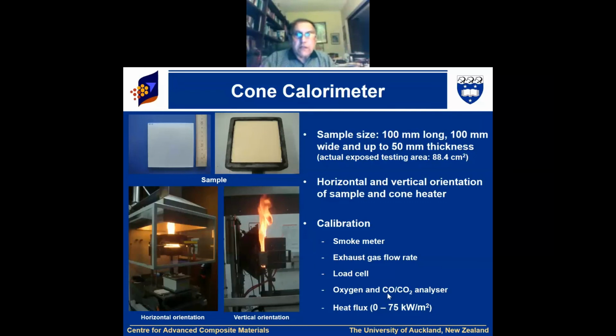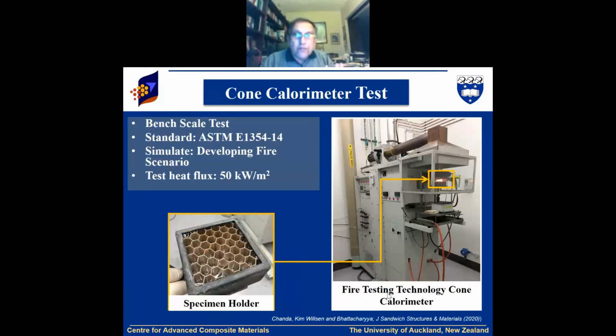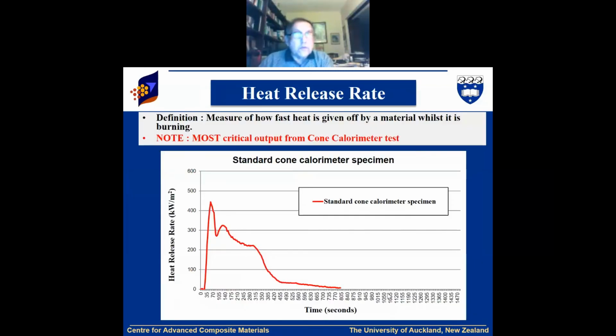So we have got the cone calorimeter, exhaust gas, load cell, oxygen, and heat flux can vary from 0 to 75 kilowatts per square meter. The sample size is specified as 100 by 100 and around 50 millimeter thickness, or less than that. The actual exposed testing area is 88.4 square centimeters. They are very specific. If you don't follow that, they will not accept the result at all. So this kind of test we did, and then you get the output like that, the heat release rate, the peak heat release rate, and then how it gradually drops. Now you may drop it by using some flame retardant.